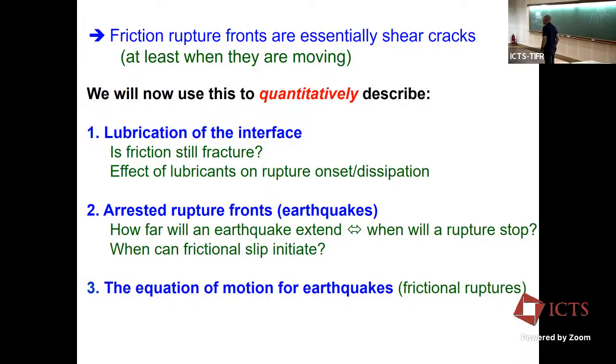Things should be subtracted out. That's why we spent an incredible amount of money to make these plexiglass plates very, very flat. So statistically, we have a continuum. Now, what does that even mean? The dissipative zone, or the distance between contacts, is a few microns. The contacts themselves are small. So as long as we're not looking too close to the crack tip, we can take our glasses off and we still see an effective continuum. Yes, we're creating new contacts, and we're breaking contacts all the time.